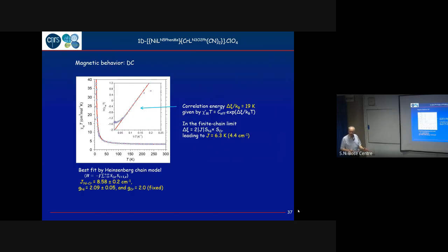One-dimensional magnetism. So in the previous case where you observed the hysteresis, that's also coming from the chain? So that means you're saying there is no long-range order. No, it's only the behavior of the chain, and the hysteresis is because you block, at low temperature, the magnetization of the chain in one direction, and it doesn't flip. To flip, you have to apply a stronger field to reverse the magnetization. This is why you have this hysteresis. And you will see in a coming example, and even later, in the last example, there is 3D ordering. And you will see it's a clear signature.